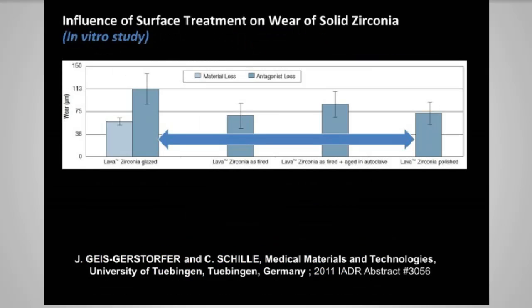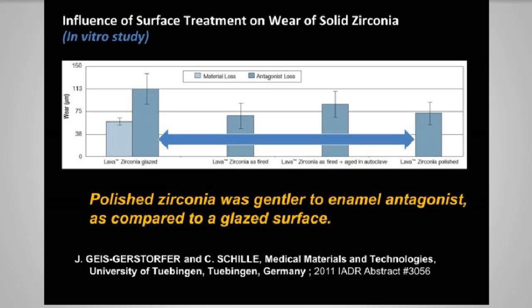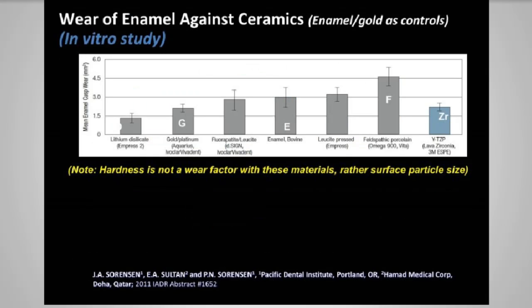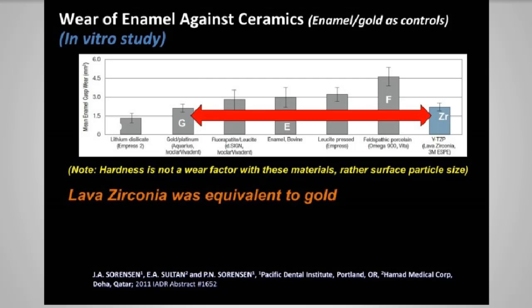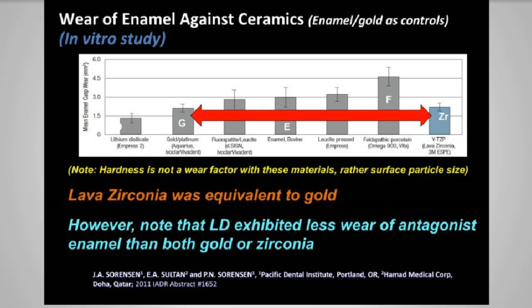Here's another study that very well shows polished zirconia was gentler to the enamel antagonist as compared to a glazed surface. Another study, Lava zirconia was equivalent to gold. If we compare across the chart here, Lava zirconia polished, equivalent to gold. But look what sits on the far left, right over here. You'll note that's lithium disilicate. And we talked about this in part 1. Several studies in part 1, including the one I showed you at the University of Alabama. It notes that lithium disilicate exhibits less wear of the antagonist enamel than both gold or zirconia. So if you want the very best wearing, this is still our choice right here. Although, let's not kid ourselves, this is excellent wearing when you can compare to gold. Okay?